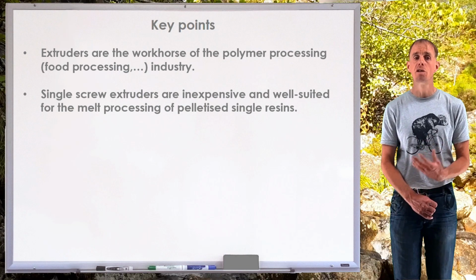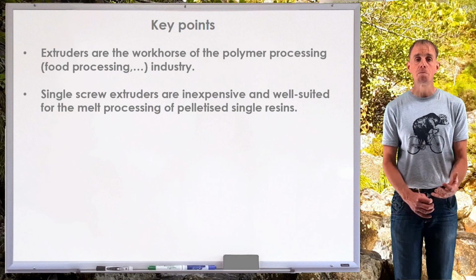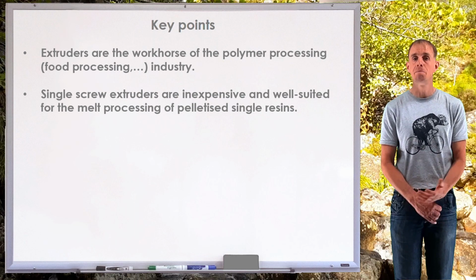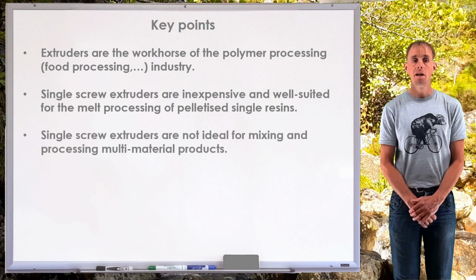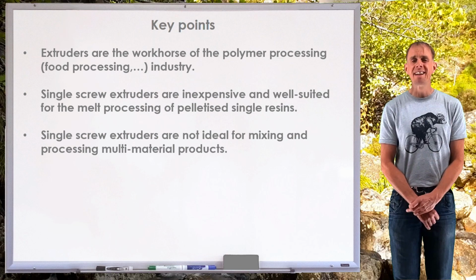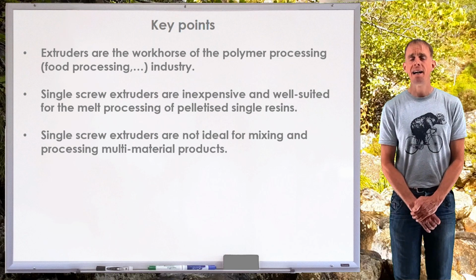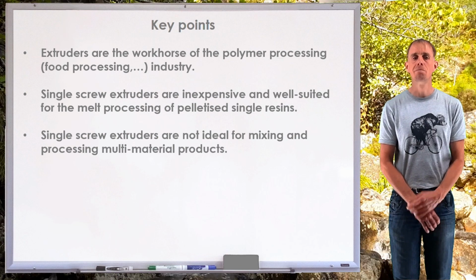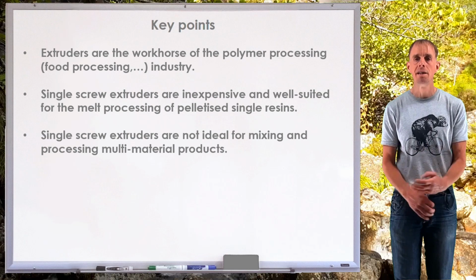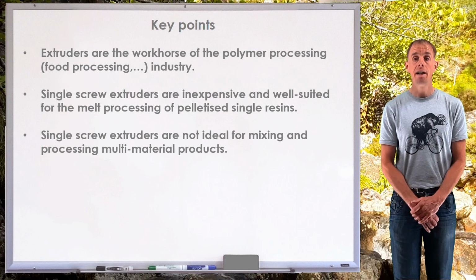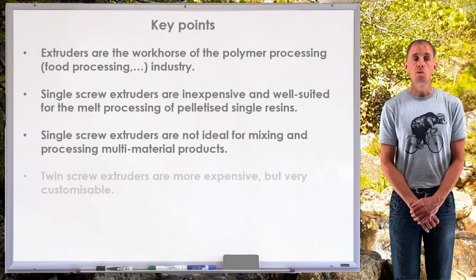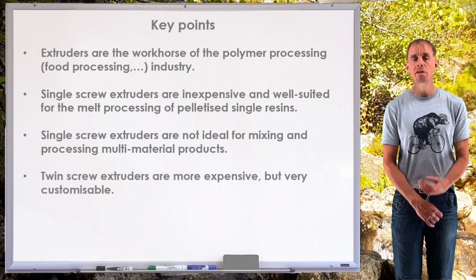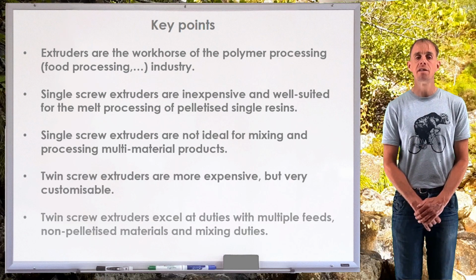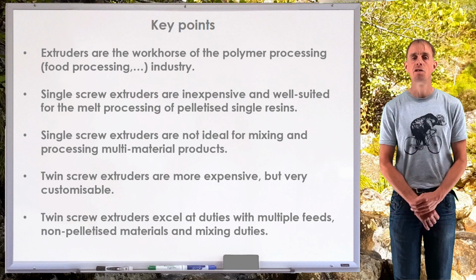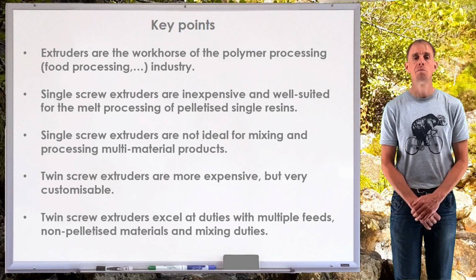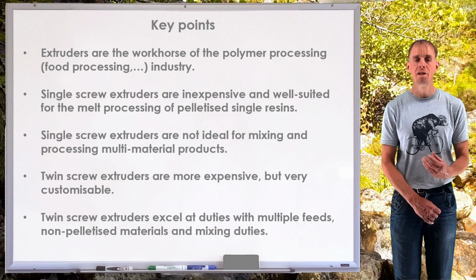Typically, you've got two machines. You've got single screw extruders, less expensive, well suited for melt processing of pelletized single component resins. They're also a little bit poor for mixing, and they're not so strong with processing multi-material products where you need to add many materials into the same extrusion line. Twin screw extruders are more expensive, but they're very, very customizable and very, very adaptable, and they tend to excel at duties where you've got multiple feeds, non-pelletized materials, and those systems that need a lot of mixing.